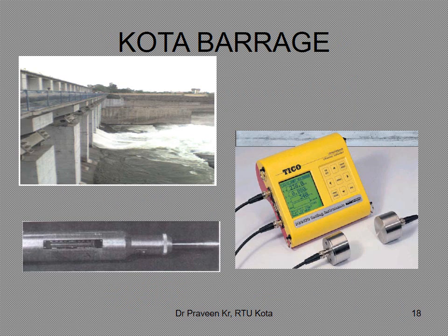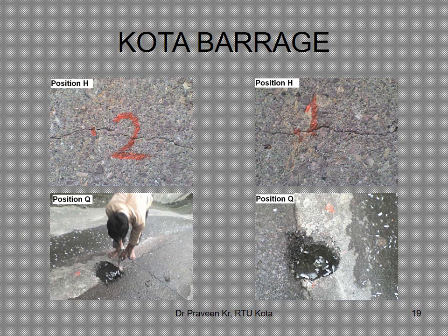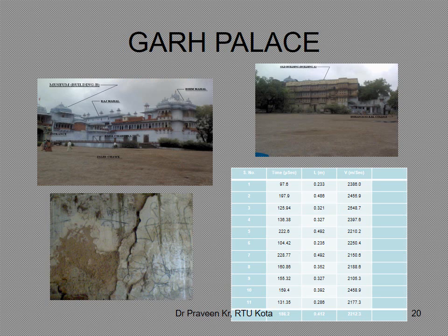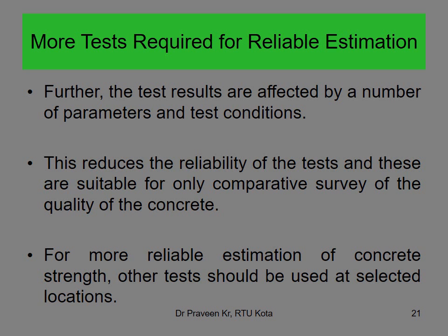We used this UPV and rebound hammer for assessment of the Stilling basin of the Kota barrage about 12-13 years ago. Some minor cracks were observed in the Stilling basin platform. Our students went downwards, took readings by the rebound hammer as shown in this third position. Similarly, they went to Garh Palace structures, took UPV readings at so many places at that time, 13 years ago. However, more tests are required for reliable estimation.